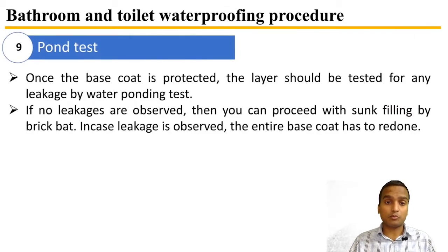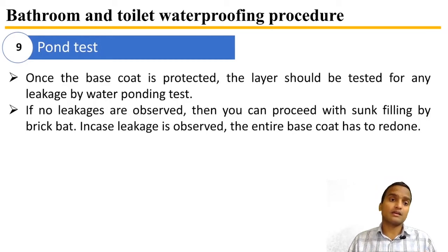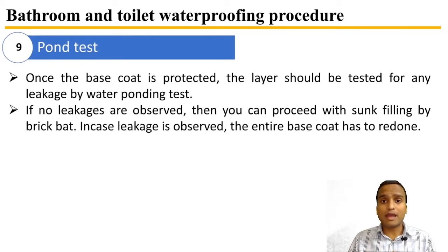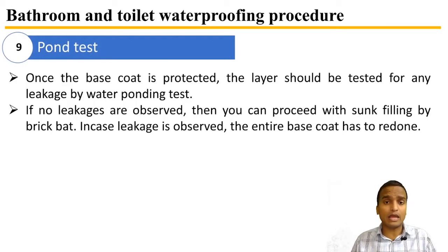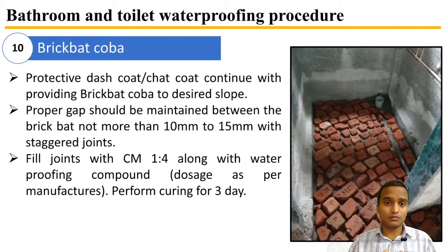We pond the entire sunken region again, and after two days, if no leakages are observed, we may proceed to fill the sunken area with brick bats — broken pieces of well-burnt normal clay bricks. If leakages or dampness are observed, the entire base coat has to be redone. This is why waterproofing of bathrooms and toilets requires alertness; proper time must be given for curing and application of coatings.